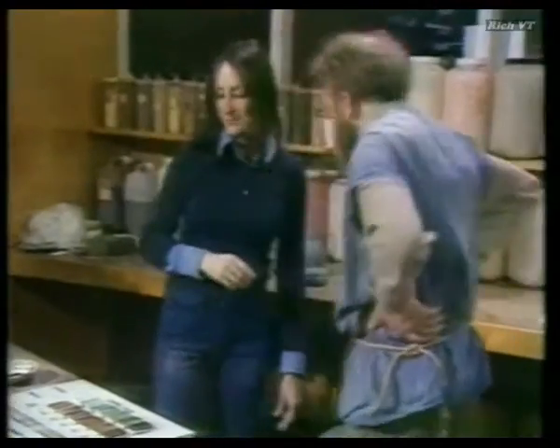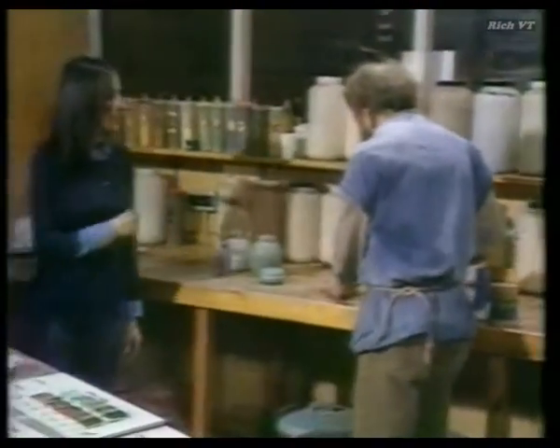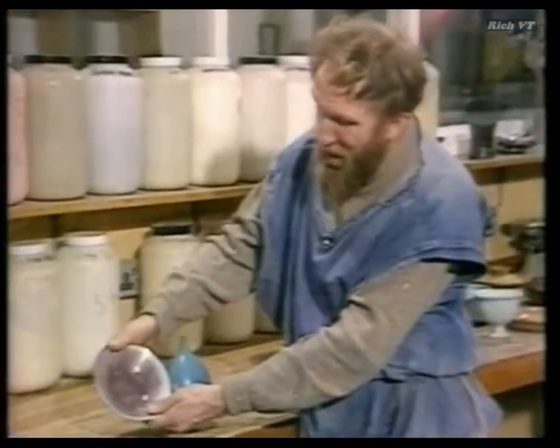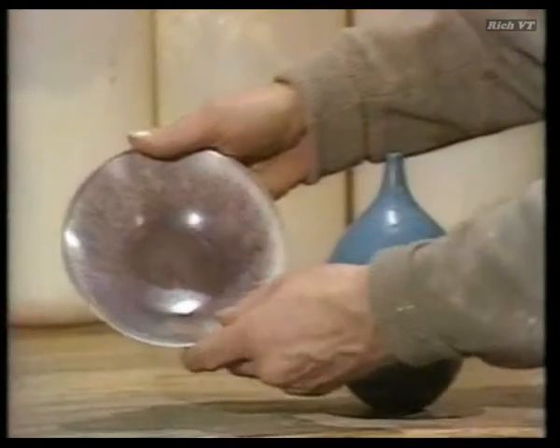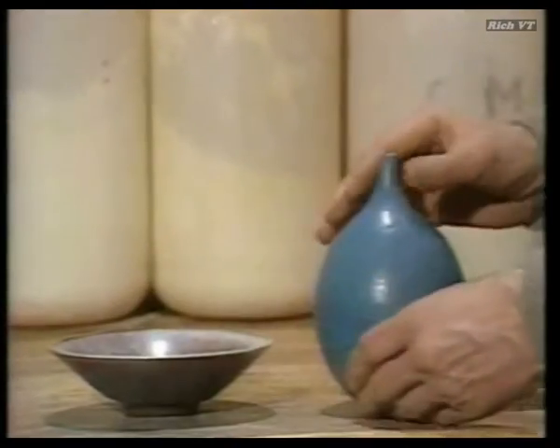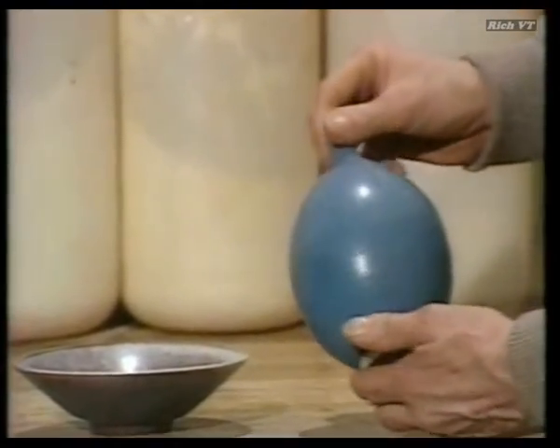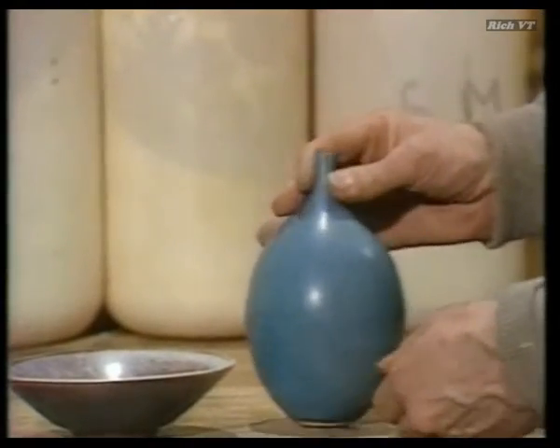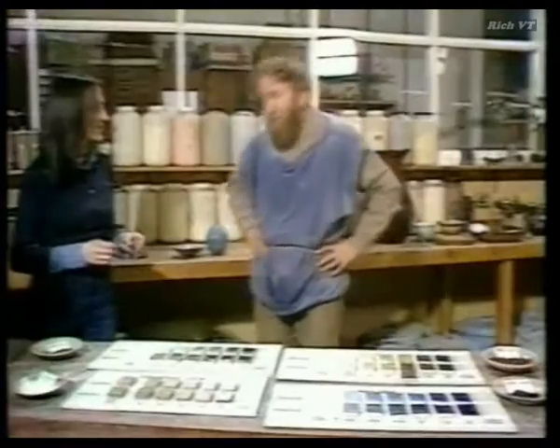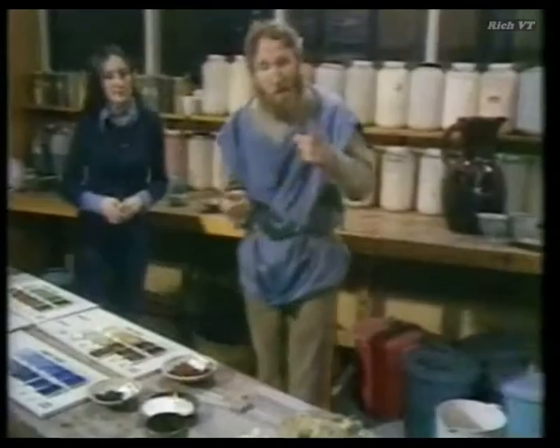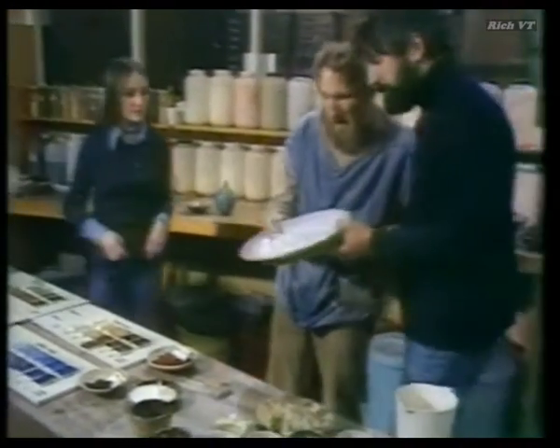If you look at these two copper pots, for example, here we've got the difference. The Colin Pearson dish is a mottled pinky plummy colour, whereas this John Parker bottle is a rather mottled turquoise. So it's a question of doing lots of trials. Very important. I think a lot of potters tend to put a few glaze trials into every kiln they fire. Yes, I do. I have a trial in every kiln. They don't always go right, but at least I record them and I can take account of what's happening to these defects.